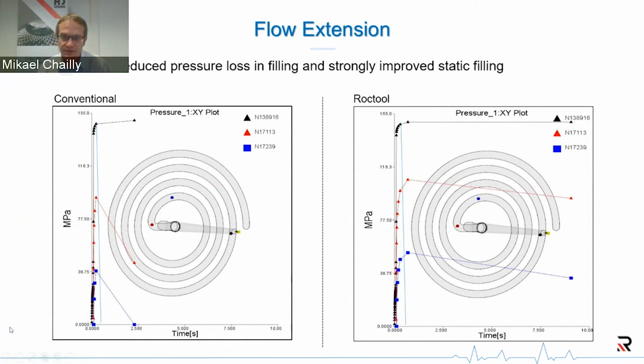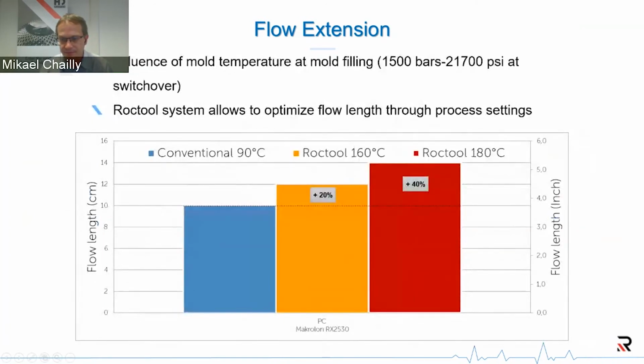And if we go to the next one, you can see that we can also improve this flow length extension, because here we have seen results about 20% at 160 degrees C for Roctool conditions versus the conventional one.